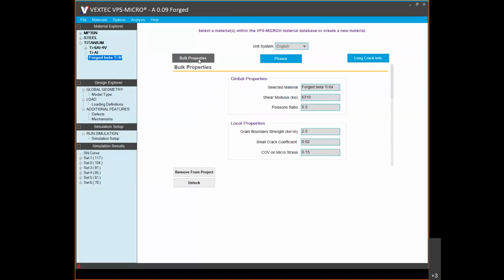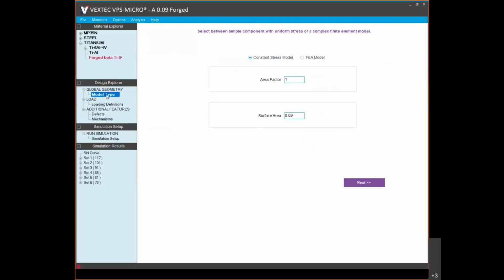Below the Material Explorer, you'll see the Design Explorer. And this is where inputs such as global geometry are found. As you recall from our example, we'll be modeling constant stress fatigue specimens with a gauge surface area of 0.09 square inches. If we wanted to model larger specimens, we could use the area factor here and put in a value greater than 1. If we wanted to model more complex geometries like notches, bolt holes, or the like, we could use outputs from a commercial FEA package like Abaqus and ANSYS. Vextec has developer partnerships with these organizations.